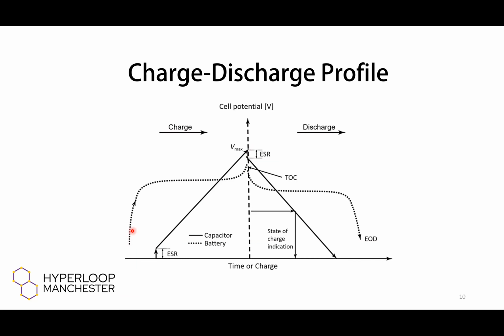In contrast to this, there's the battery, which is the dotted line going along here. And this shows a profile, a plateau, where you start charging the cell and then it starts accepting ions into the structure, the lithium ions in the lithium-ion battery, into the structure of the material. And that happens at a constant potential. They just keep shuffling deeper down into the structure, and you hold the cell at that potential, and they keep on shuffling in until it starts to get full.